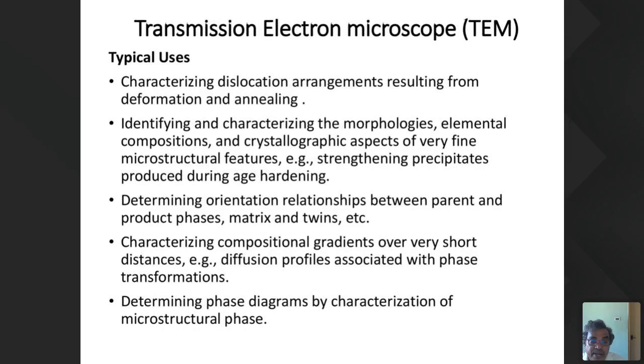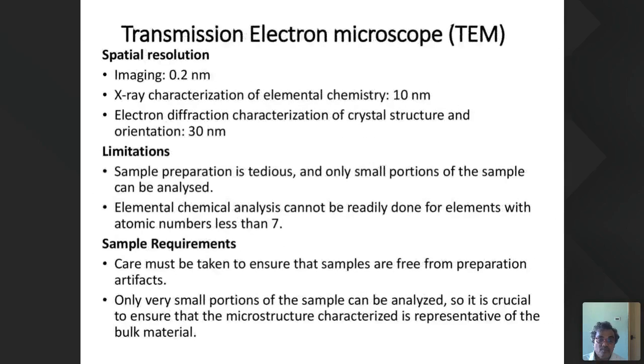Typical uses: characterizing dislocation arrangements resulting from deformation and annealing; identifying and characterizing the morphologies, elemental compositions and crystallographic aspects of very fine microstructural features, strengthening precipitates produced during age hardening; determining orientation relationships between the parent and product phases, matrix and twins, etc. Characterizing compositional gradients over very short distances, like diffusion profiles associated with phase transformation. Determining phase diagrams by characterization of microstructural phases. Spatial resolution is 0.2 nanometer for imaging, 10 nanometers for X-ray characterization of elemental chemistry, and electron diffraction characterization of crystal structure and orientation on the order of 30 nanometers.